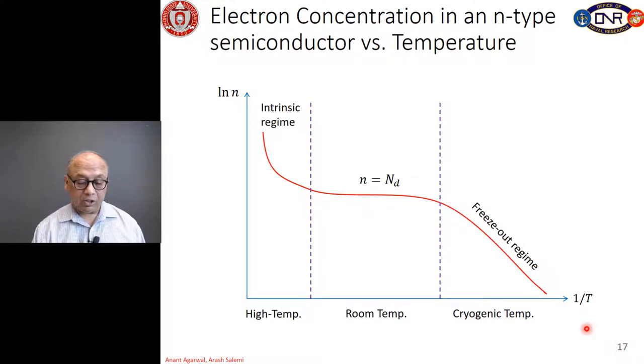Now, as we raise the temperature, on the left-hand side, we see we have a lot of intrinsic carriers, which is the result of electrons jumping from valence band to the conduction band. So the Ni value increases as a function of temperature as we had seen earlier. So at some point, the electron and hole intrinsic carrier concentration will be equal to the donor atom density Nd. And then the number of electrons and holes at higher temperature will exceed the donor atom density.